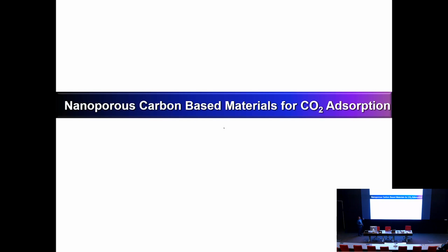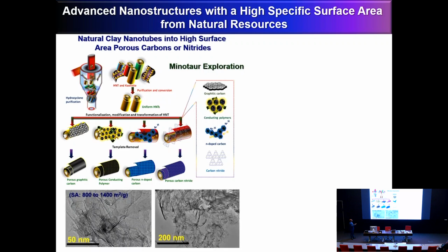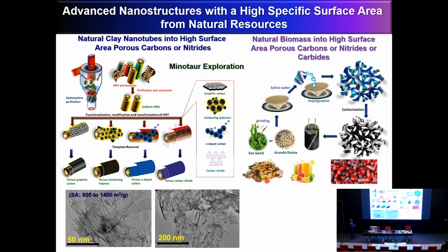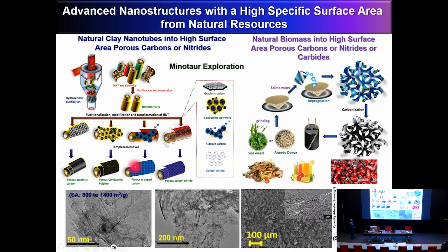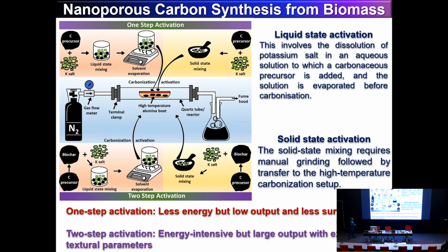Yeah. So the other device in the ultimate clean energy storage conversion is carbon capture. What we have done is we use naturally available resources like halloysite nanotubes, which are naturally available and have nanoporous structures with a very high surface area. We use them as a template to make different carbon-based materials. And also, we use waste biomass and integrate it with a two-step salt-assisted strategy to make the carbon material with a surface area in the range of 4,000 to 4,500 meters square per gram. So we use this two-step activation technique, the solid-state activation technique.